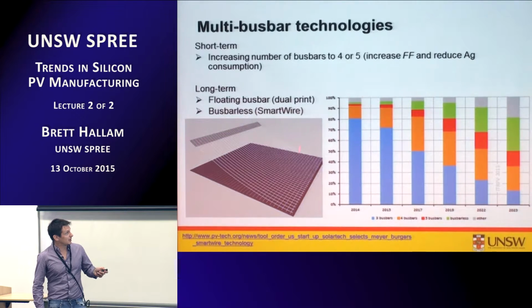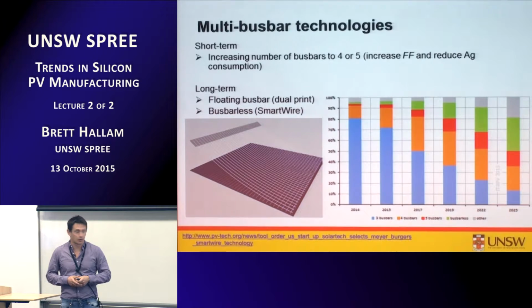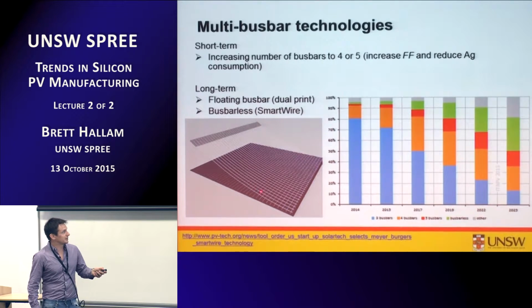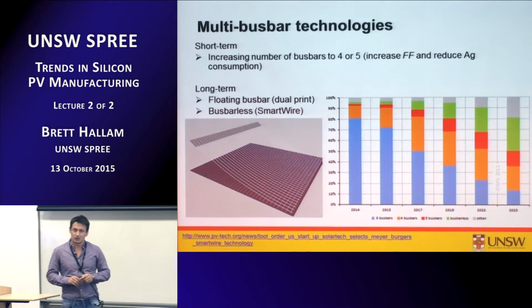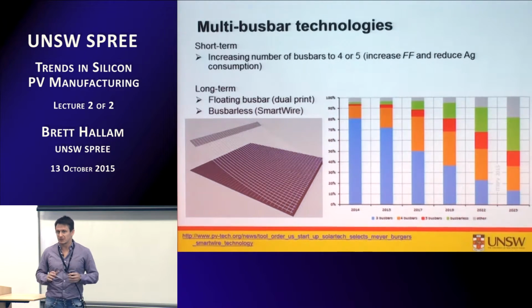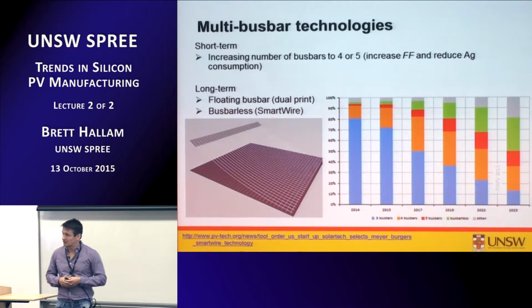So I've got a picture here of Meyer Burger's SmartWire technology. With a screen-printed solar cell with just fingers, we have an encapsulant material which has copper wires embedded in it. During the lamination process, the sandwich is made in the laminator, you heat it up, and there's a certain reaction. Typically these wires are coated with, say, tin bismuth alloys with very low melting temperatures, so they can make the electrical contact to the fingers underneath. This is one technology that's looking promising, although there are probably mixed reports over some of the costing. You might have a bit more information on the actual cost.